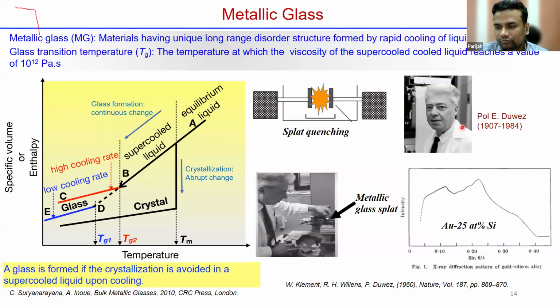His job was that when we melt a material, it becomes liquid, and he would undercool or rapidly cool that liquid into solid form. He used to calculate the degree of undercooling, or supercooling, and how the structure would change. One day he was carrying out an experiment with an alloy of 75% gold and 25% silicon. He mixed 75% gold and 25% silicon, melted it and made a liquid. Then he made a drop of the liquid, and when the drop fell, he splatted it. By doing so, what he was essentially doing was very rapidly cooling that liquid.